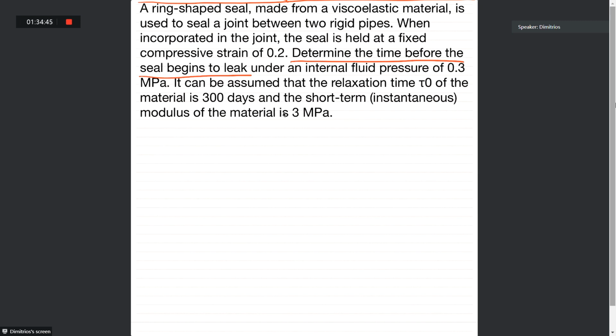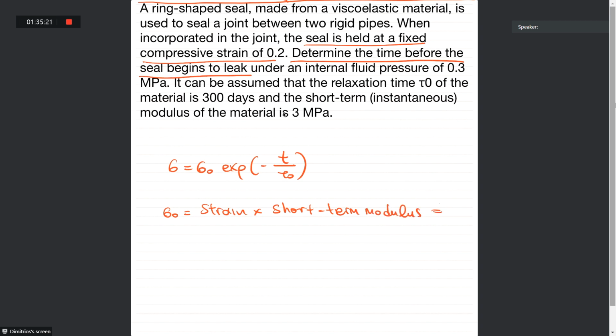So we're talking about relaxation, okay? Because we're saying that the seal is held at a fixed strain. So we're talking about relaxation. The most appropriate model for relaxation is the Maxwell model, which is sigma equals sigma 0 exponent of minus t over tau 0. Well, sigma 0 is equal to strain times short-term modulus. So sigma 0 equals 0.2 times 3 megapascals. This is a modulus, not sigma 0 as some of you put. So 0.2 times 3 megapascals, that is 0.6 megapascals.